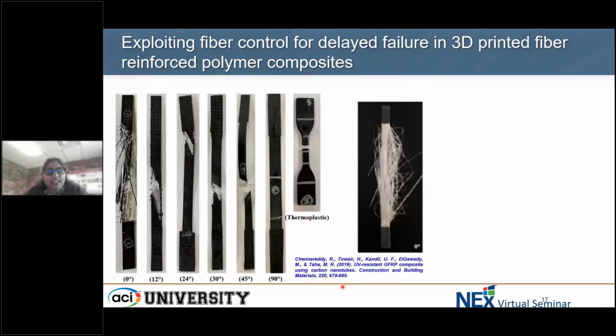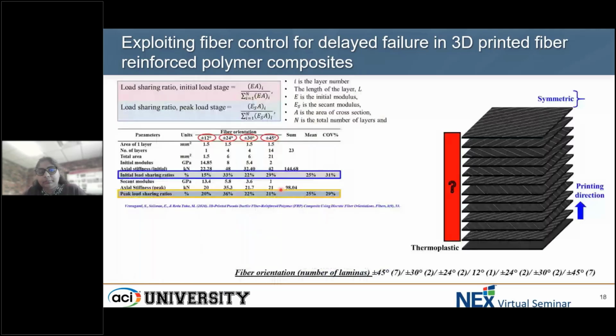So if we look at the failure modes of these composites, 0 degrees fails pretty well when compared to a traditionally manually fabricated fiber reinforced polymer composite. So that typical broom-like failure has been noted. So you can definitely say that 3D printed composite fails in a similar way to manually fabricated composites. The other angles, which are very cumbersome to achieve in a manually fabricated setup, we were able to achieve in a 3D printed setup. So you're able to get the fiber orientations and the properties that they demonstrate.